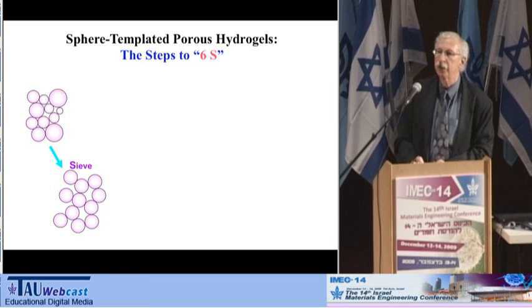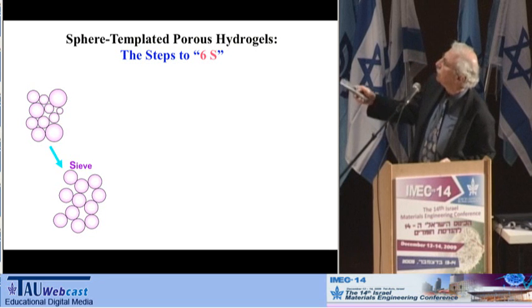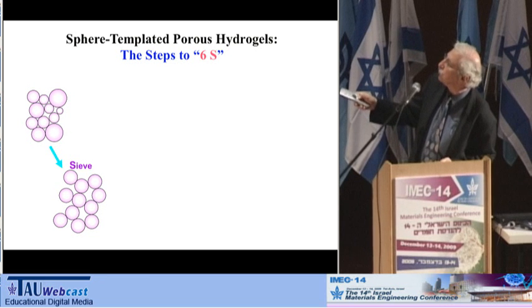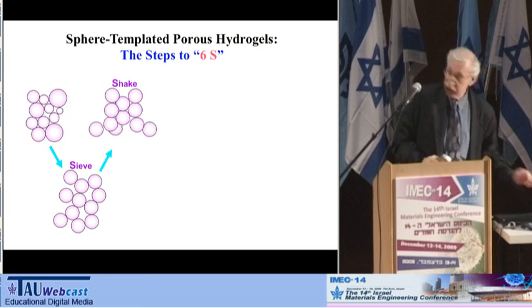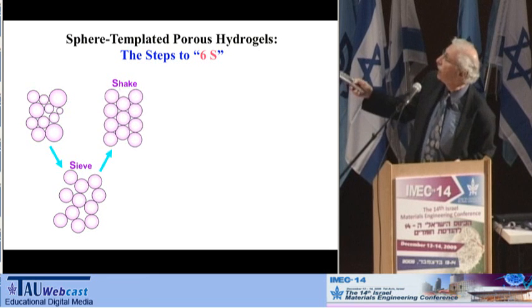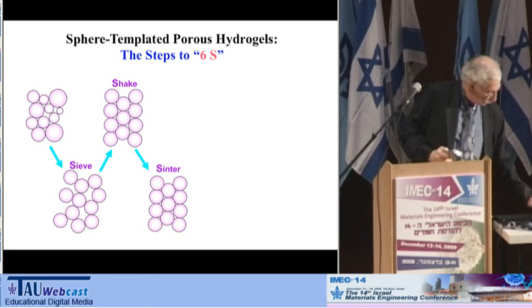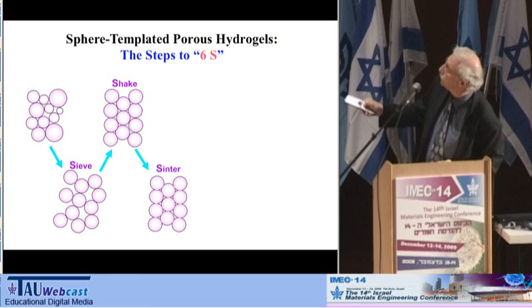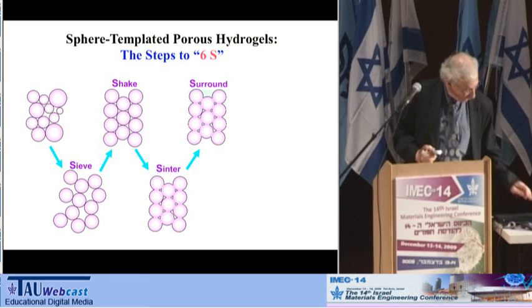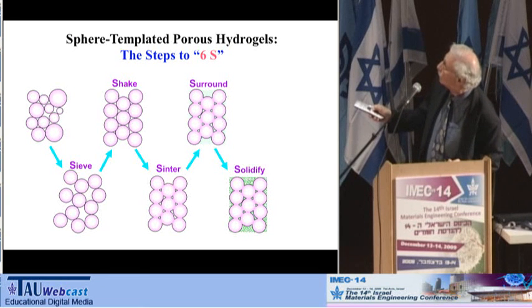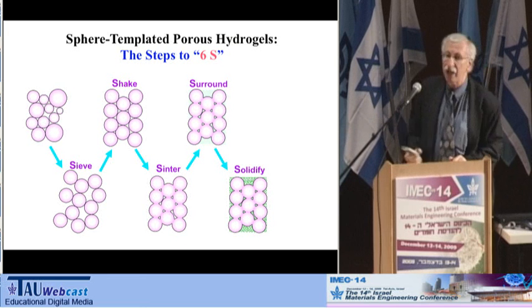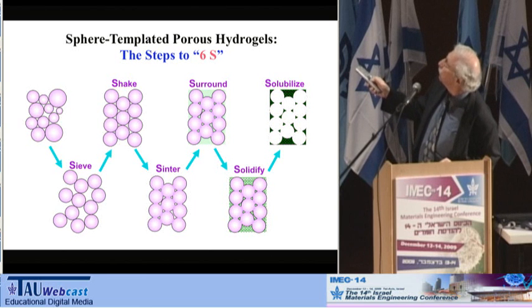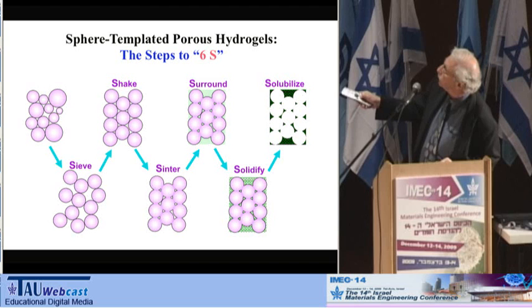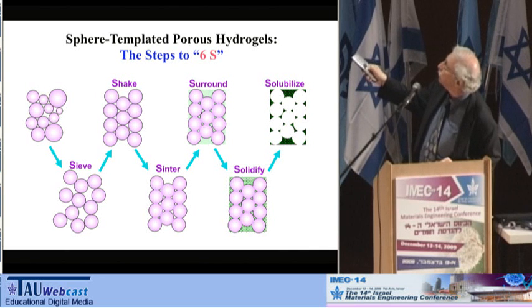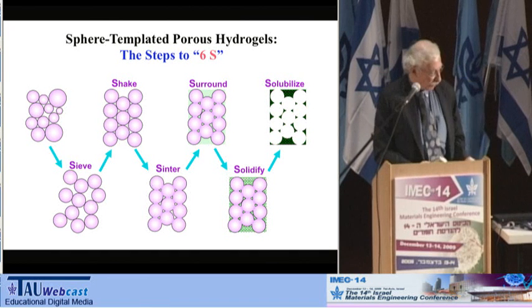And so what we did was develop a technology that was borrowed from some other templating methods, but applied to tissue engineering. We took some microspheres, these are in the micron range, and we sieved them to get very fine cuts. And then we ultrasonicated them so they settled down into a tight-packed, close-packed array. And then we gently heated them so they sintered or fused into a mass. And then we surrounded them with a monomer liquid. Then we solidified or polymerized that monomer liquid. And finally, we used a solvent to extract out the spheres. So what we're left with is an interconnected structure, interconnected where the spheres were sintered together, an interconnected structure where every pore is the exact same size, and that was kind of what we wanted.